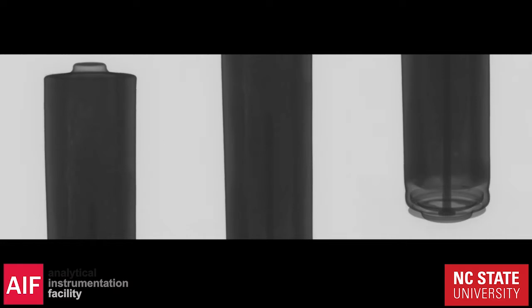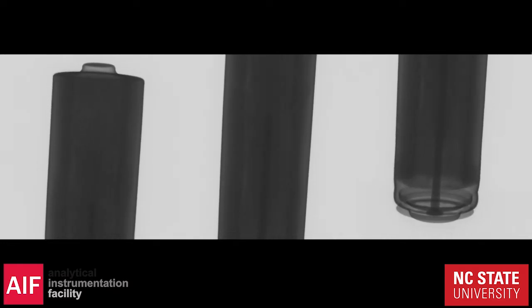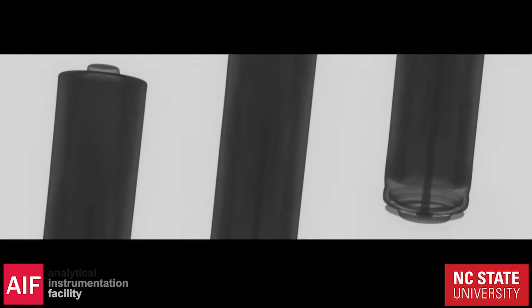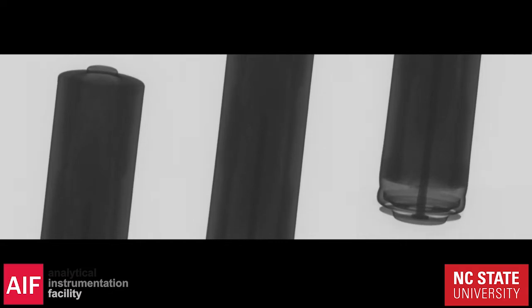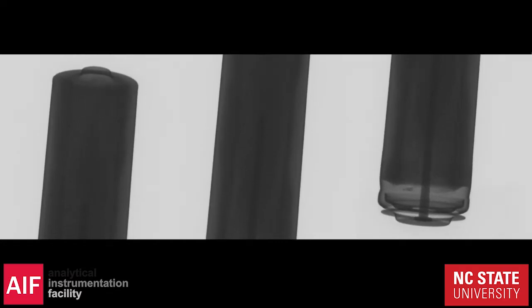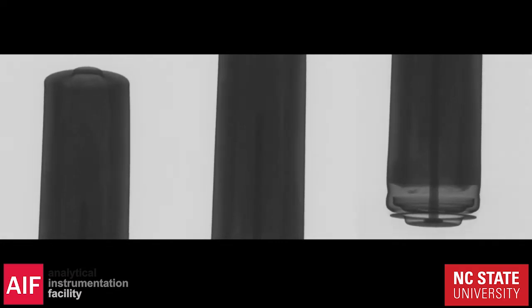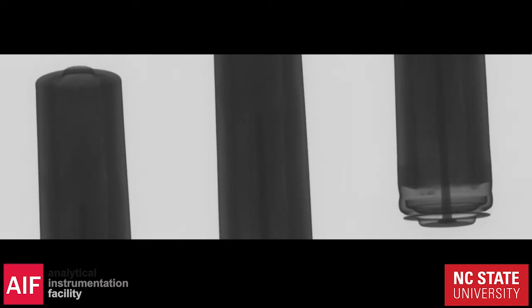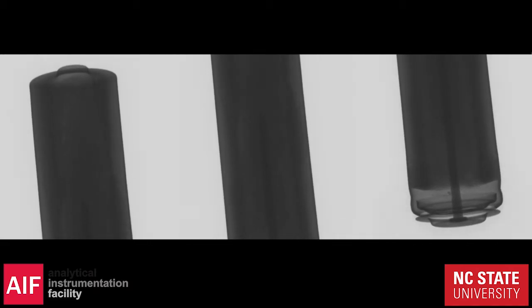Here we can see the resulting 2D radiographs of the sample as it is being rotated. The specific sample was scanned in 3 sections that were later stitched together. We could scan the entire sample at once, but this way we could achieve a higher resolution. These projections are now reconstructed into a 3D volume.